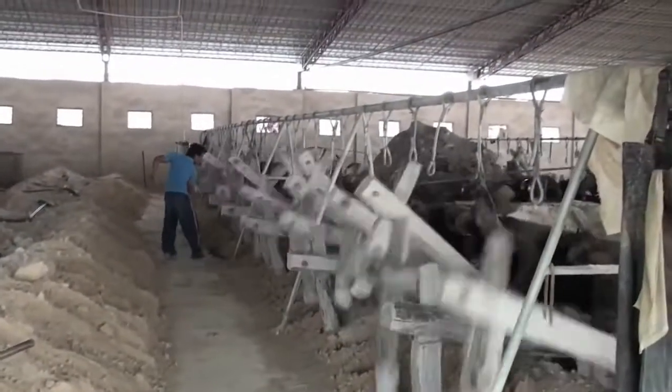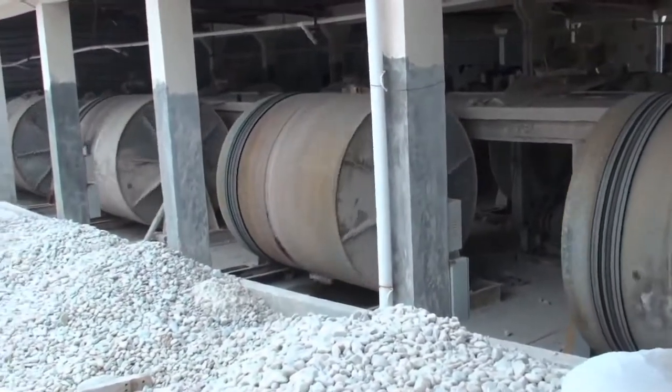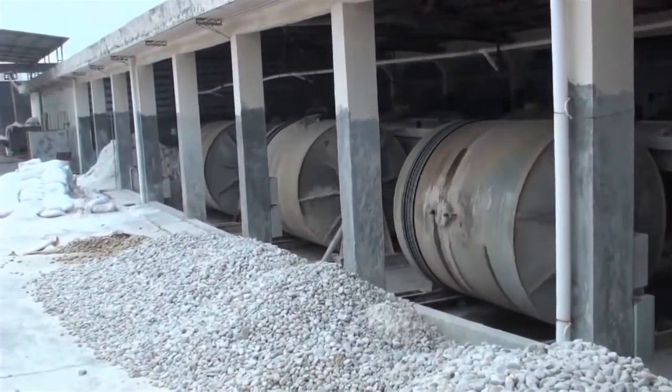The powder is refined, first in dry processes that remove impurities such as iron ore and other metals. And then they'll pump that through a magnet, giant magnets to take any iron content out. Because if there's a little piece of iron in the clay, when it goes into the 1500 degree oven to bake, that iron will explode and you'll get pops and cracks. And so they have to make sure that there's no iron in it.